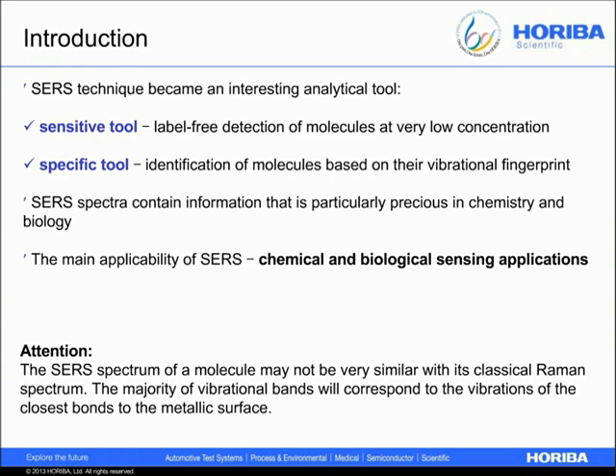For example, there are chemical sensors for the detection of traces of pollutants and contaminants in food and water. And also there are biological sensors or biosensors for the detection of biomarkers, which are key molecules in cancer diagnosis. But keep in mind that SERS is a vibrational technique, and be careful: the resulting SERS spectrum of a molecule may not be the same as its classical Raman spectrum. This is because the enhancement will be maximum for the vibrations coming from the closest bond to the metal.